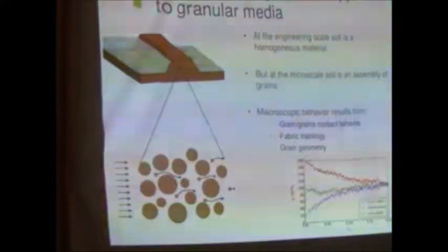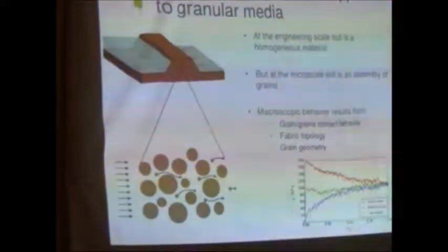And these three basic ingredients give the granular media its macroscopic constitutive mechanical behavior. On this bottom image, these are typical results you can obtain with a drained triaxial compression test with the same grain size distribution and the same contact law. The only thing that changes is the geometrical configuration, which presents very different types of mechanical behavior.